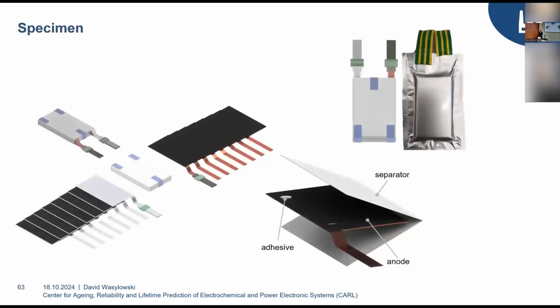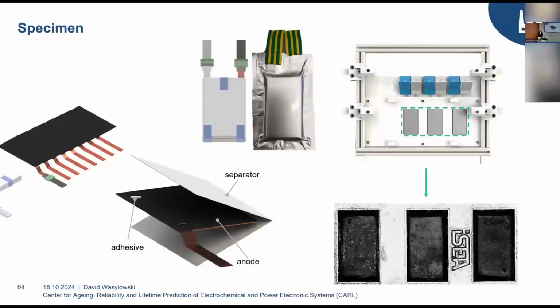And this is what we did together with a project partner. We tried to reconstruct this battery cell we saw on our first image with these adhesive dots and this Z-folding procedure, and we tried to make a battery cell which is really close to what we saw first, and now visualize it using our reflection technique. So we got a bunch of cells from them, we put them in our scanner, and if we would now just scan this marked area here, for example, using our method described earlier, we would get this image down here visualizing one slice within this 3D image. So this is, for example, the first anode being visualized.